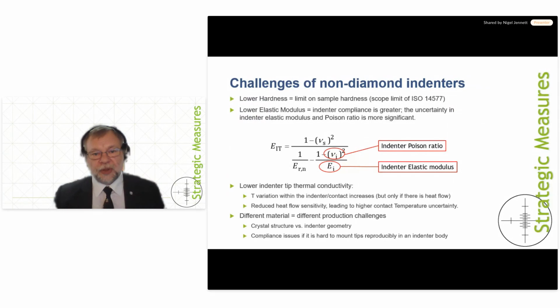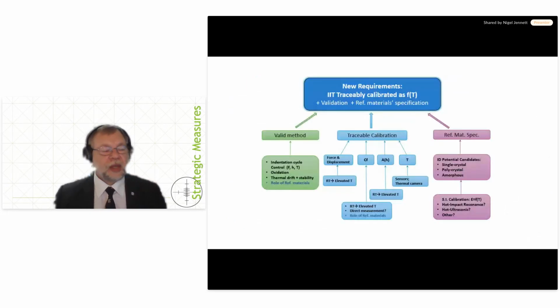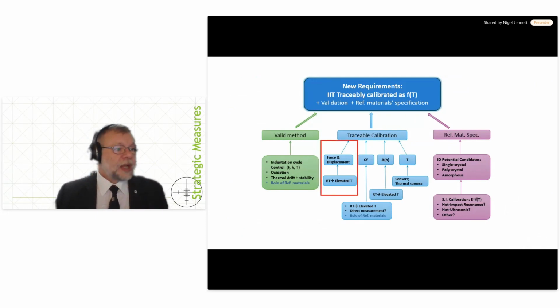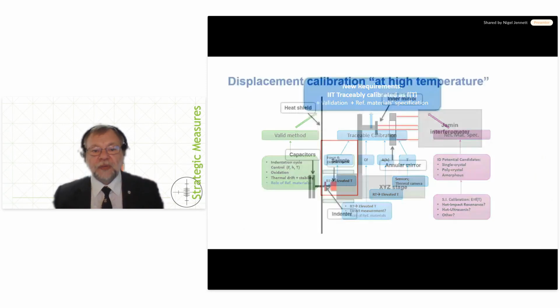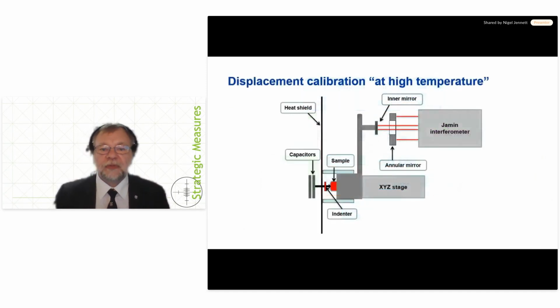And it's got a lower thermal conductivity, and we'll see that there are some consequences for that. And of course, there may be different production challenges. And one of those is, can you stick it into an indenter body with a low compliance and a reproducibly low compliance? If not, then you're going to have a rickety indenter, which is going to give you variable results. So moving on, we've got part of the way, and I'm still looking now at how do we just look at the calibration. Well, that's quite straightforward. We do exactly the same as we did before. In our case, we used an interferometer. We monitored the movement of the stage, which pushed the indenter, which changed the capacitor spacing, which measured the displacement.